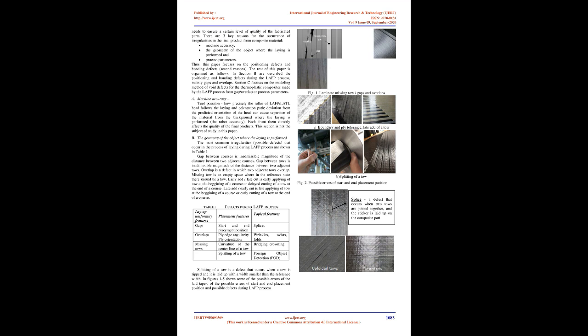Hanapel et al. have shown clear differences in terms of ply wrinkling between unidirectional CF/PEEK and carbon/polyphenylene sulfide, CF/PPS, using a carbon fabric for molding of complex part geometry. They observed that the UD material had more difficulties in conforming to 3D geometries, and they highlighted the fact that both types of composite cannot be deemed similar when considering the processing cycle.